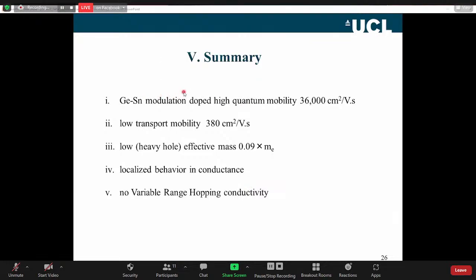these germanium-tin modulation doped structures, they have a high quantum mobility, 36,000. That would be characteristic of the type of germanium that perhaps had a transport mobility of 1 million. This system, we've got this order effect, transport mobility is 380 cm2/V.s. So that is high enough to give us quantum oscillations on metallic type. We get the effective mass for free in this material. This measurement gives us an estimation of the effective mass from the thermal damping of the oscillations. It's about 0.09, so it's nice and light.